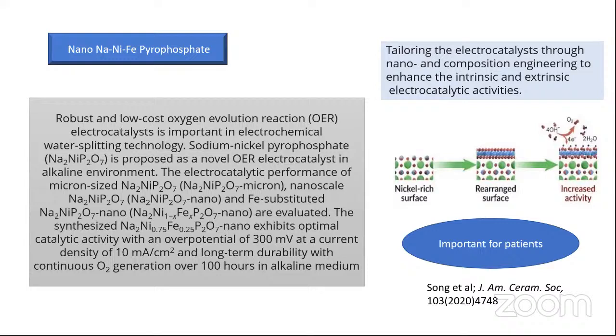Sodium nickel pyrophosphate is proposed as a novel OER electrocatalyst in alkaline environment. The electrocatalytic performance of micron size, nanoscale, and Fe substituted phosphates was evaluated. So there is another, nanoscale sodium nickel pyrophosphate, and the last one is iron substituted, the sodium nickel iron pyrophosphate. So all the three have been evaluated.